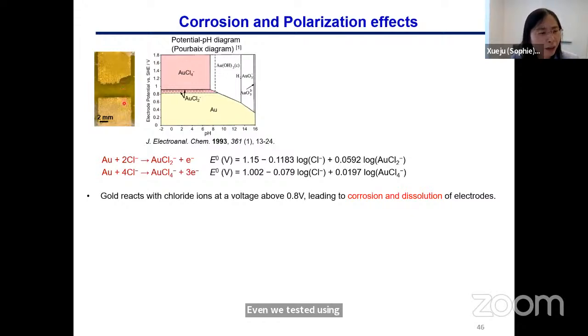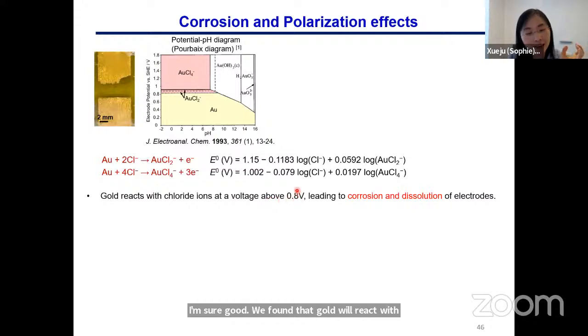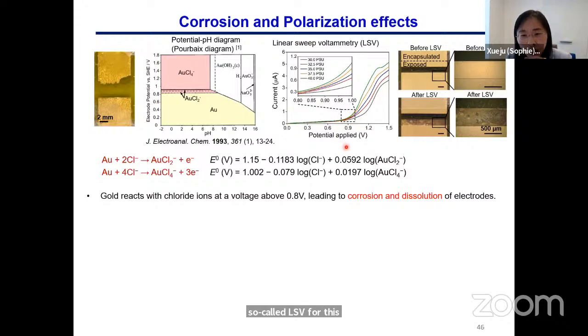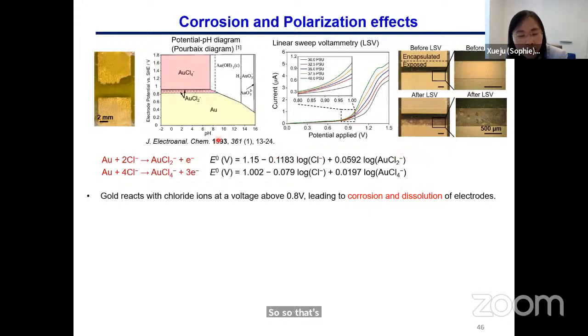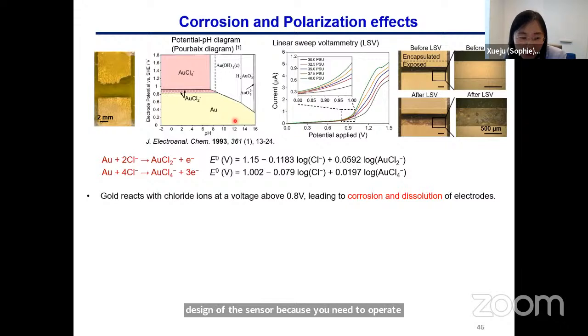At the beginning, we were very confused. And we went back to the electrochemistry of gold. We found that gold will react with chloride ions at a voltage above 0.8 volt. This leads to corrosion and dissolution of the electrodes. This is further confirmed by using so-called LSV, linear sweep voltammetry, for scanning of the electrodes under different salinity levels. You can see that after testing above this 0.8 volt, we have some corrosion of the electrodes. So that's very important for the testing and the design of the sensor, because you need to operate below 0.8.